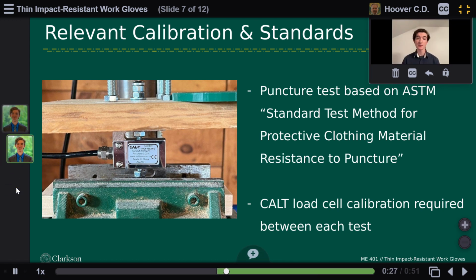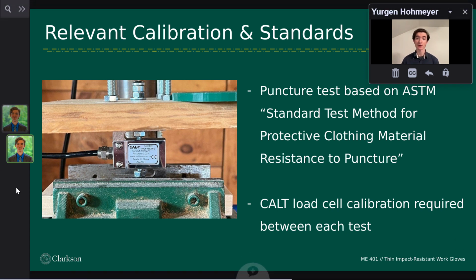The puncture test used in the project was based on the ASTM standard test method for protective clothing material resistance to puncture, albeit with a number of modifications for simplicity and due to the equipment we had available. In terms of relevant calibration, the load cell and HX711 board required calibration between each trial, which was accomplished by using a known weight to adjust the gain factor on the HX711.